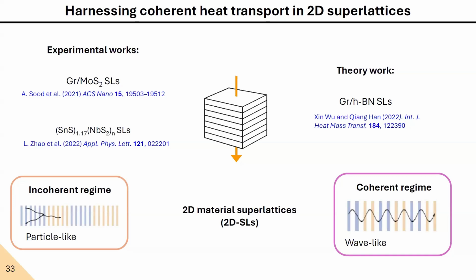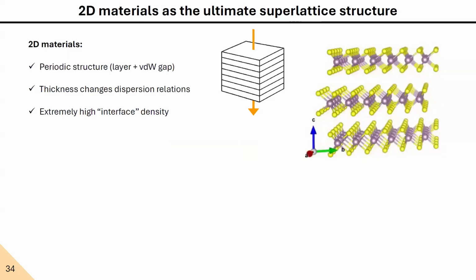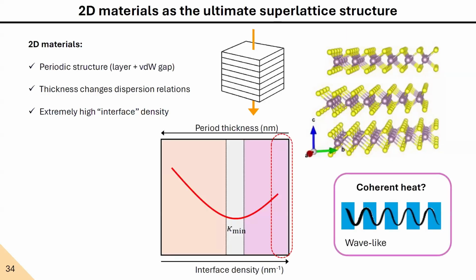In any case, a theory work appeared where they study graphene hBN superlattices, and they demonstrated a similar crossover from incoherent to coherent transport. But wait, isn't a 2D material already a periodic structure? It seems so. This is made of layers and van der Waals gaps. When we change the thickness, the dispersion relations change, not introduce more resistant channels. And these materials have the highest interface density available in the realm of material science. So these materials would fall on the extreme end of this graph, implying that phonon heat should behave as waves.